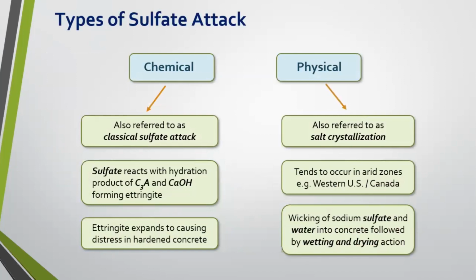On chemical sulfate attack, this is also referred to sometimes as classical sulfate attack. This is when sulfate reacts with the hydration product of C3A or tricalcium aluminate and free lime or calcium hydroxide. And the product that's formed with this is ettringite. Now, the problem with ettringite is it's expansive. And so when this starts to form, as we all know, concrete's typically in some sort of restraint. And when you've got this restraint and now you've got expansive forces, at some point you're going to be looking at cracking, and cracking opens our concrete structure up to all sorts of nasty things that mean harm.